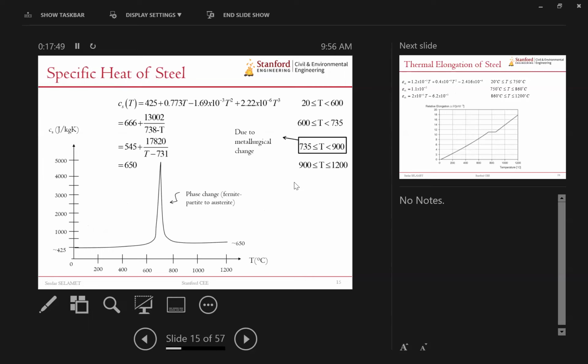Specific heat, on the other hand, will start at around 425 and end at around 650, but it does have this peak, this spike, which only occurs when the steel changes its phase, and it's due to a metallurgical change from ferrite pearlite to austenite. So we don't have to know about all this chemical engineering or metallurgical detail, but we know that because of that phase change, it becomes harder to increase the temperature of steel. Okay, it requires much more energy, I would say, 10 times more energy. Even if you input so much heat into it, it just doesn't increase its temperature.